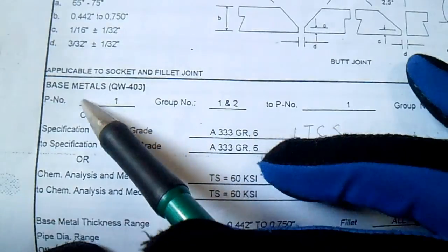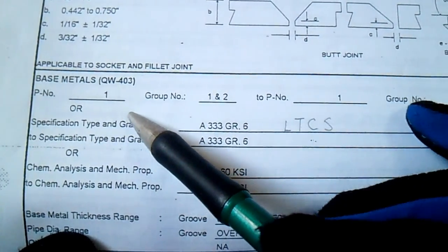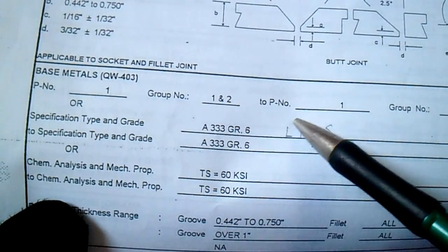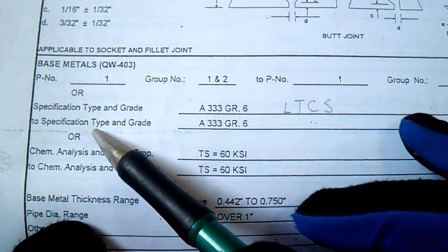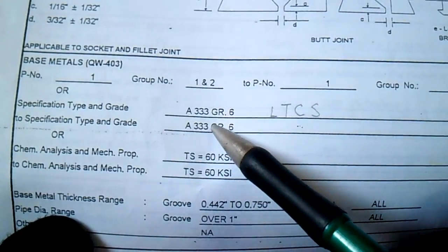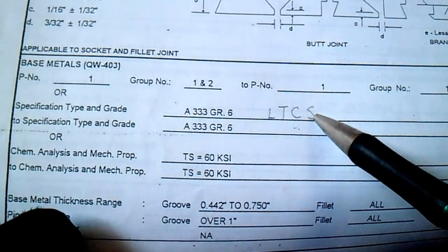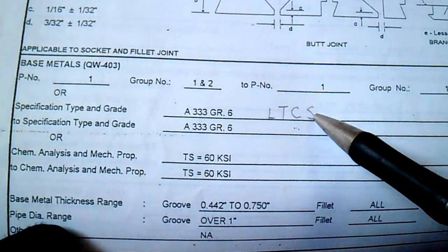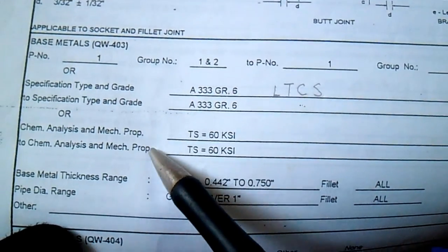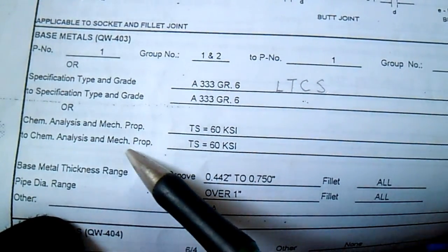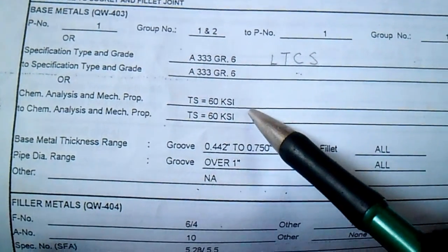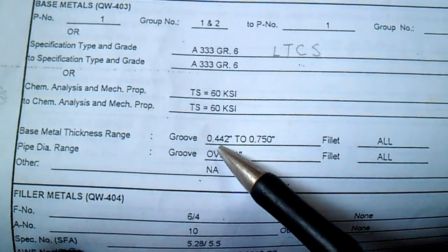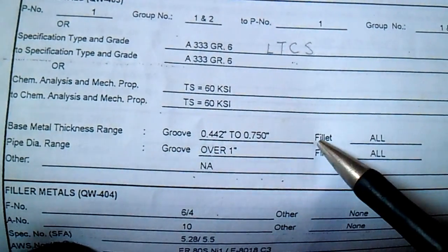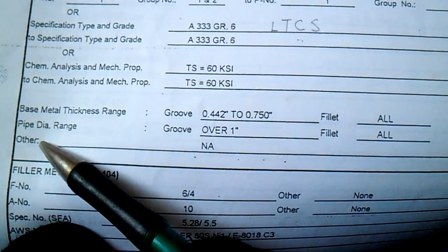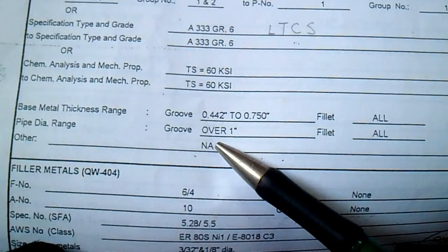And also we have base metal, so they are using P number 1, group number 2. So this is specification type A333 grade 6, so this is LTCS. So LTCS is low temp carbon steel. Okay, so they have chemical analysis. So our base metal thickness is 0.442 inch, fillet all. So diameter of pipe is over 1 inch. Okay,